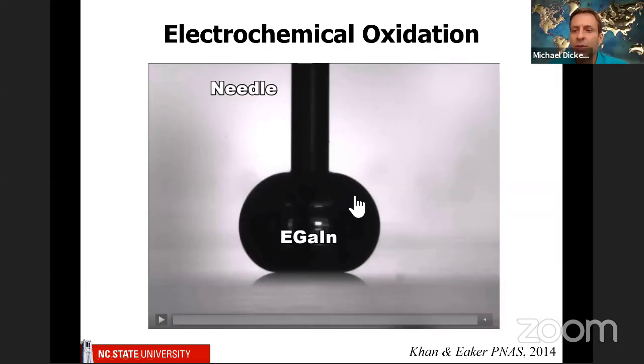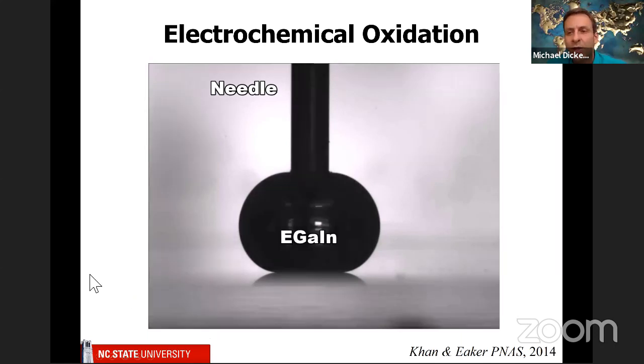So this is a droplet of eutectic gallium indium sitting in sodium hydroxide. So there's no oxide layer. And we're going to apply +1 volt, which in principle, what you should expect is that the surface should oxidize maybe a few nanometers, which means you're not going to see it, and nothing will happen. But we did this experiment, and you can't see the counter electrode. It's sitting somewhere out of the field of view.